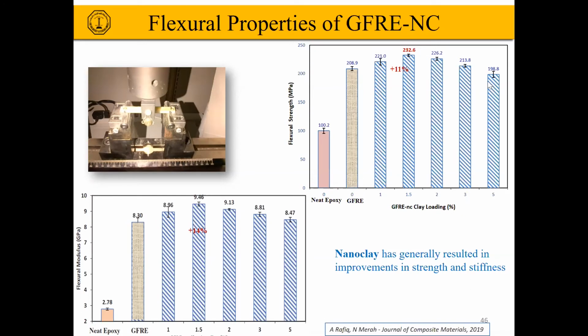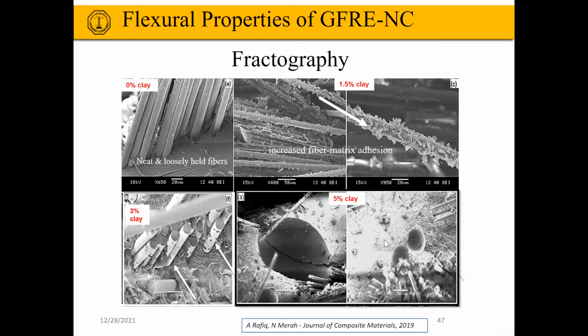But as you go higher and higher, because of the presence of clusters and stress raisers, the flexural strength reduces. The same thing can be said about the flexural modulus. 1.5% increases the flexural modulus by about 14%. So we can say that nanoclay generally results in improvements in strength and stiffness of epoxy glass fiber material.